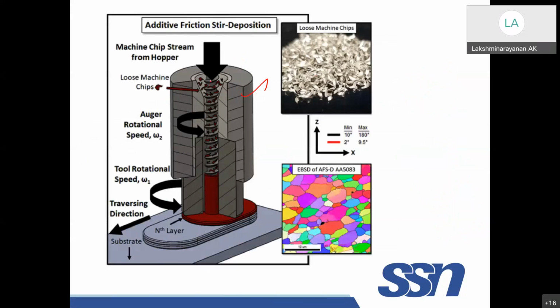You have a hollow cylinder, inside you have a screw which is rotating at a different speed. So whatever the particles, they will be forced through here. So it will pass through this path. There is a gap. So this is also rotating. Because of that, there will be frictional heat generation, and it will go to a plastic state and be deposited. Okay. So you can do one layer, 2 layers, 3, like that it will go. You can have different layers deposited. From the powders, machined chips also you can deposit. Recycling is one of the very important concepts, especially, as I told at the beginning, magnesium chips. If you want to recycle them, you can still recycle them by this method.